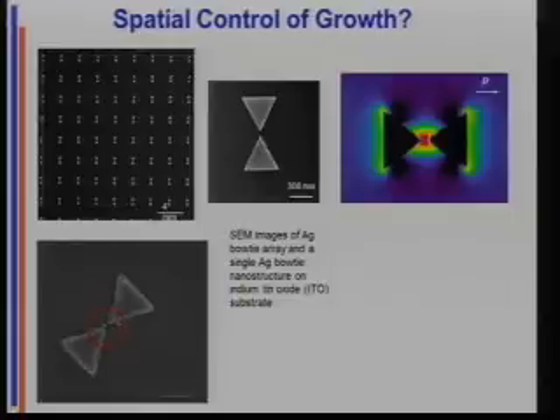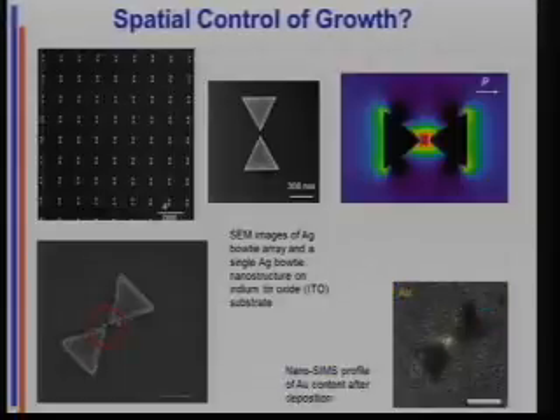See that and see this. Those two are little gold nanoparticles grown on a silver bow tie by irradiating with this polarization where it should be right there. And that's really kind of cool, okay? And if you don't believe that, here's the NanoSIMS profile of gold after deposition, and there's the intensity of the gold. You can see the bow tie there as a shadow after the deposition. So we have at least the initial hints that we might be able to do directional growth in this way, which is cool. Okay.